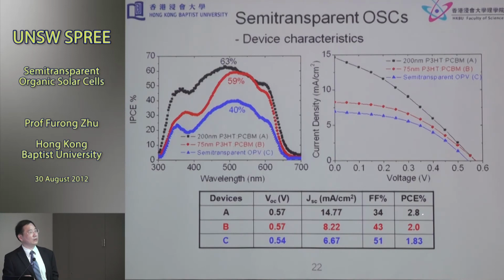this was a little bit old data. Now we can get over 3%. This is 2.8%. And then device B is also a control device fabricated with a 75 nanometer thick blend layer, but with a non-transparent aluminum layer. Then we see this is the maximum you can get, about 2% with this thin layer. But if you replace aluminum with ITO, then you get about 1.8%. At the same time, this device is about 30% transparent. So these are very encouraging results.